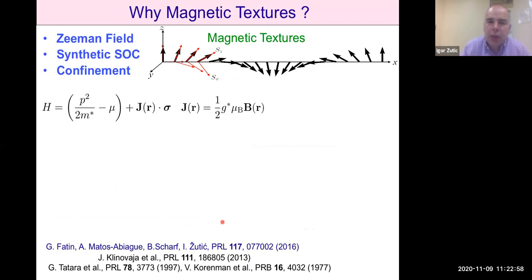So first, let's try to understand why magnetic textures. At once, they provide needed ingredients for Majorana states. They provide a Zeeman field. That's of course expected because we would remove spin degeneracy, but they also provide synthetic spin orbit coupling. So even if our material does not have spin orbit coupling, it can be effectively induced through these magnetic textures, and we may even create confinement. So what this sketch shows is that we can understand the role of these magnetic textures inhomogeneous magnetization by rotating the quantization axis along the direction of magnetization.